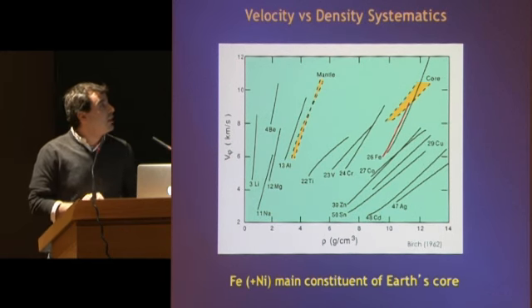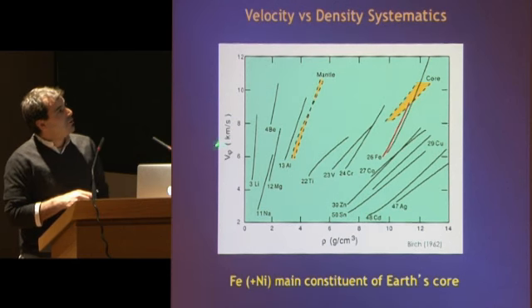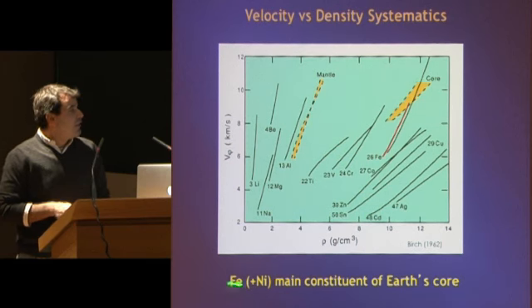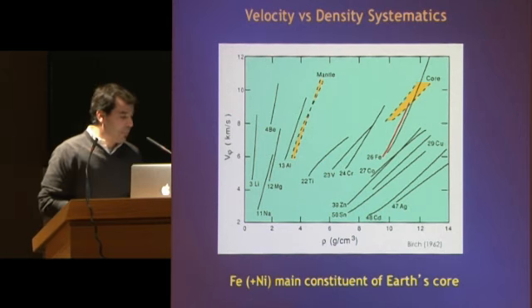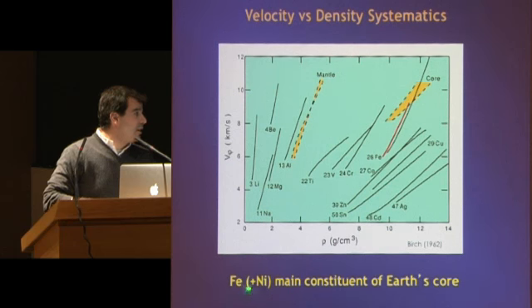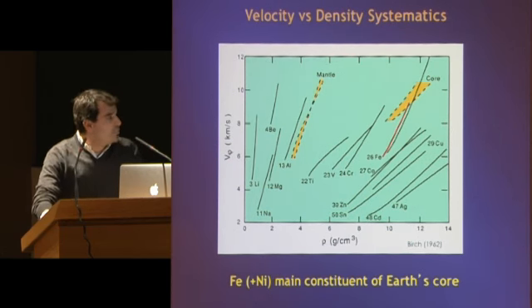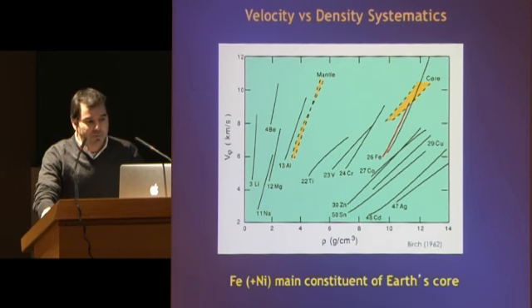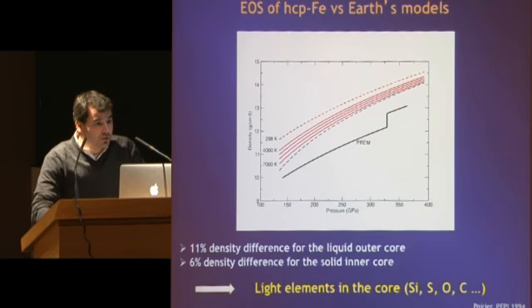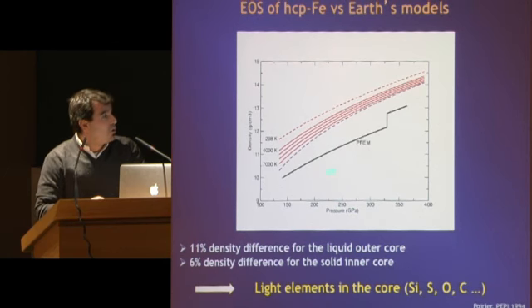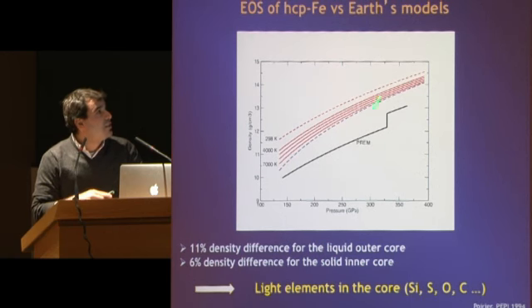Starting from shock wave measurements and looking at velocities versus density systematics for several elements, Birch suggested iron to be the main constituent of the Earth's interior. Now, from cosmochemical abundance, we know that nickel has to be present and alloyed to iron up to a few weight %. But at first approximation, the inclusion of nickel does not significantly change the elastic properties of iron. However, a closer look at the equation of state of iron with respect to what is observed by the seismic model, here comparing the density as a function of pressure, highlights a quite significant density difference. Either in the outer core or the inner core, hcp iron is too dense with respect to seismic observation, and this is irrespective of possible temperature correction.